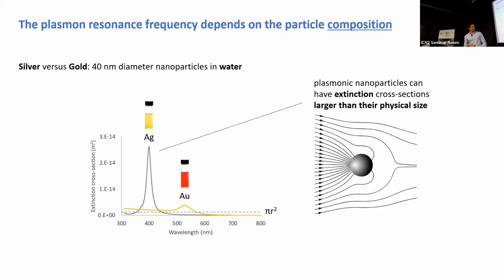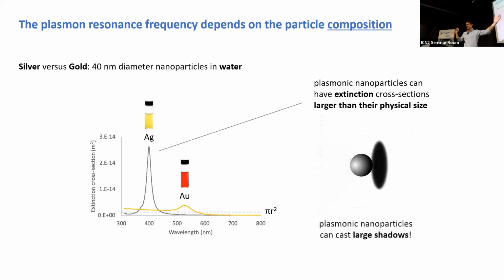And so some people depict it using Poynting vector lines. Essentially, plasmonic nanoparticles can have extinction cross-section larger than their physical size. The way I tell it to my students is plasmonic nanoparticles can cast large shadows. They have giant egos. And if you tune it properly, they can cast a big shadow behind them.